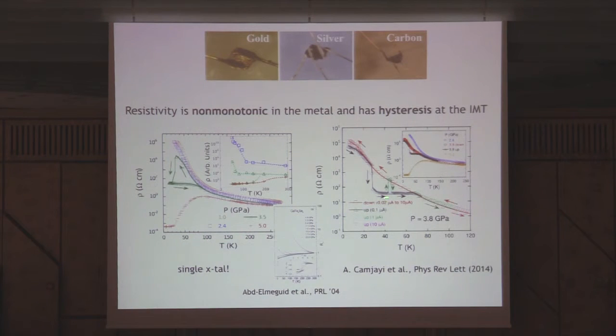So moreover, when he got into this hysteresis regime, he did something very smart, which was to lower the current. So he got into this metallic state and then increased the current again. And by increasing the current, you locally heat. When you locally heat, the system jumps in resistivity. This is destroying the quasi-particle peak. This is evidence of, or consistent with destroying the quasi-particle peak and going nowhere, anywhere, but just on the insulating branch. And then once in the insulating branch, you can go down and then lower the current again, lowering the local heating, so the system jumps back again to the metallic branch. So you see that you have really bistability between two well-defined states.